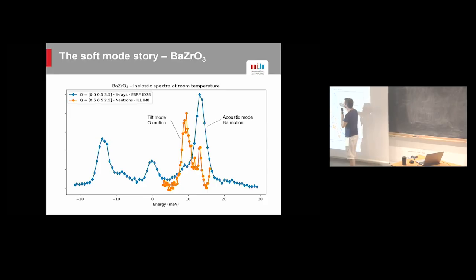So this is essentially what you see in X-ray because it's the heaviest element in the perovskite. And the other one is the tilt mode, the one that involves only oxygen. And this one in X-ray, I mean, if you do a fit, you can see it, but essentially it's really not strong at all. So if you only have that, it's a bit doubtful. But in neutrons, it shows up super nicely.